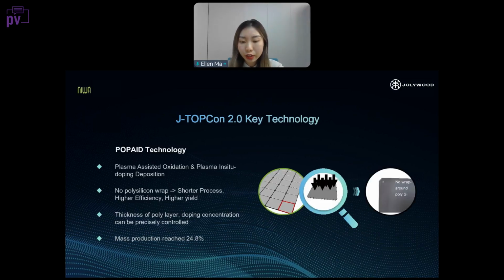So under this situation, Jolywood has self-developed a technology to avoid this issue, which we call TOPCon 2.0 technology. We named this technology POPAID. POPAID actually stands for plasma-assisted oxidation and plasma in-situ doping deposition. Jolywood is the first and only company to use this technology in mass production.